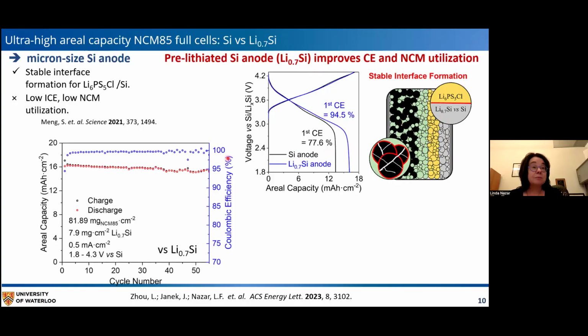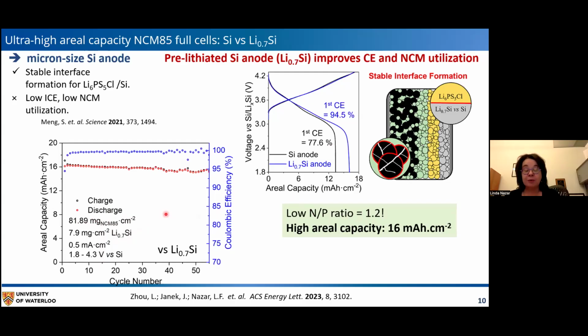And in this case, we were able to get very high areal capacities as shown here, but also as shown here. So we're upwards of 16 milliamp hours per square centimeter with a very low negative to positive ratio of 1.2. And of course, this is not at high current density because we're loading about 81 milligrams per square centimeter of cathode active material, but this is sort of proof of concept.